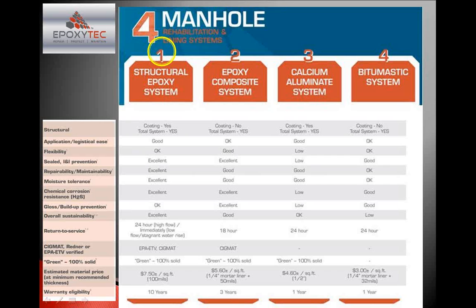It is 100% solids, and therefore passes the green test without any solvents or anything of that sort that may otherwise not be accepted. And it is eligible for approximately a 10-year warranty when it is applied by a certified trained applicator. Pricing-wise, as we can see over there on that sheet, we're looking at about $7.50 per square foot for application material only, of course. Or in terms of linear foot on a 4-foot manhole, we're looking at about $95 per vertical foot.